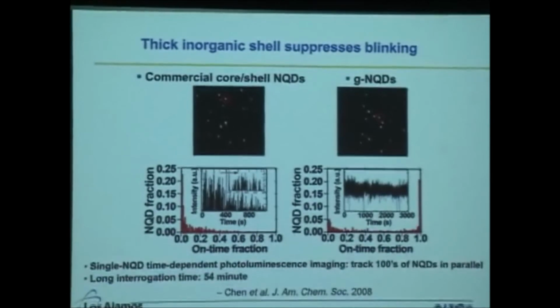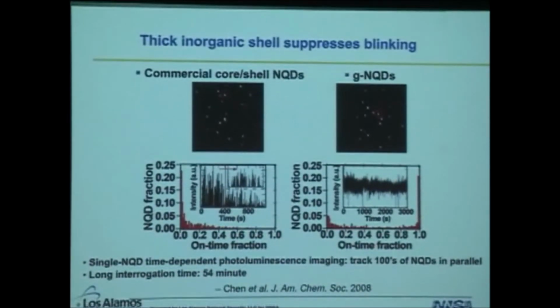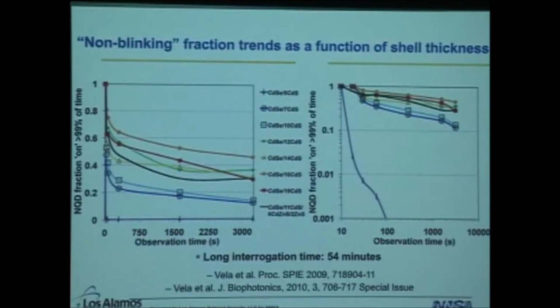But I want to point out, too, in contrast to the other couple of reports in the literature looking at thick shell effects, we really kind of torture our dots. We hit them with a laser for about an hour when we're doing these blinking studies. More typically you'll find in the literature blinking results that go on for a couple of minutes. And so I feel quite confident that we've really achieved something unique here because of how harshly we can treat the particles, and yet they still exhibit this unique behavior.